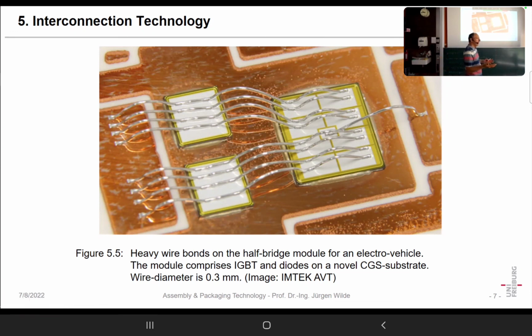The advantage is then you can distribute the current better on the diode than if you just do it with the metallization alone. After the here 1, 2, 3, then the fourth is again on the transistor here, and again we make a loop on the transistor. So we have seen we had 5 bonds in a series. That here is the gate bond. It's not necessarily a thick wire, but if we are already on the machine, we use that, of course.